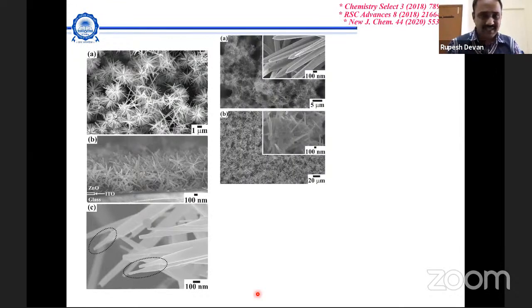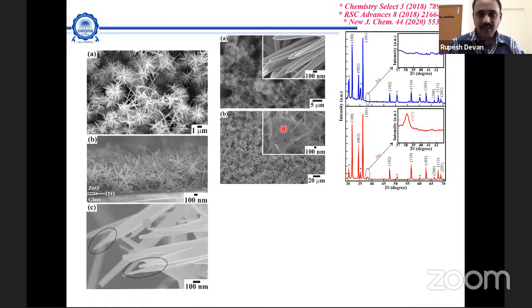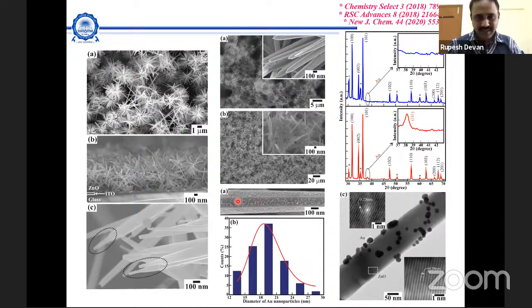First we synthesized zinc oxide nanorods in a one-dimensional format, and then we covered them with gold nanoparticles. Different reaction parameters were used. Then we confirmed that gold is really lying on these one-dimensional forms. You can see here very nicely that these gold nanoparticles are coated across the one-dimensional nanorods, and the diameter of these nanoparticles was less than 30 nanometer, which we have confirmed with TEM as well.